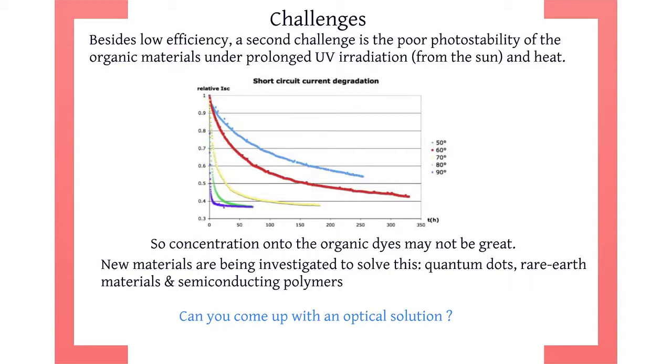My glasses are maybe about 7, 8 years old. So you can see they're starting to become more yellow. They're not white anymore. You put it against the white. And that's exactly because over 7, 8 years of UV exposure to sunlight, these molecules are degrading, the photostability. And that's a big problem with these kinds of materials. So if you want a window, of course, after 7 years, you don't want it to yellow in your house. That's a fairly big fundamental problem.